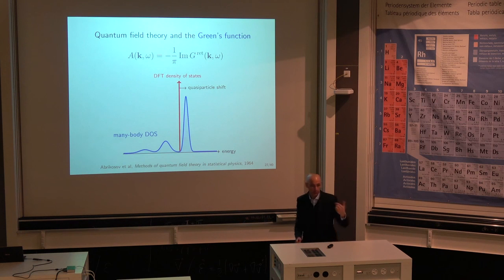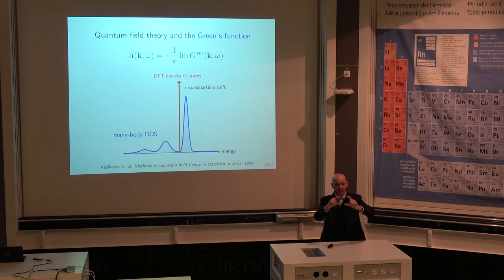So in that case, what we actually did, this is before even looking at phonons, is to show that if you study the many-body band structures of a semiconductor, and you consider this effect properly, you obtain a replica of the entire valence band coming from the plasmons. We showed that in silicon. You have a bandwidth of 20 electron volts in silicon, and the plasmon energy is 16 volts. So what you find in silicon is basically a replica of the entire band, 16 volts below. And that was actually confirmed by experiments later.